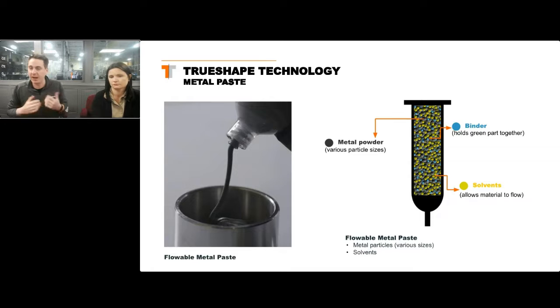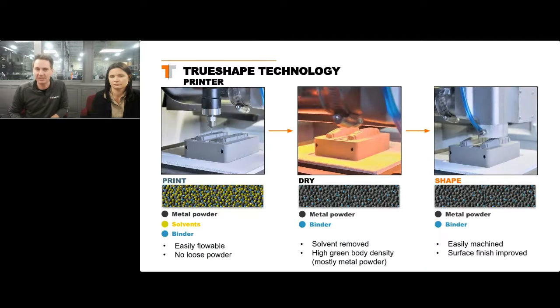And this is really a lot of the secret sauce of what makes Mantle work, inside of this paste. So every single layer inside of our printer, which is built inside of that CNC that I showed you earlier, we are printing this paste. This paste is just being extruded out of a nozzle. It's actually not even heated when you're doing this. It's viscous enough that just with a pump, it can be extruded through this needle to lay down a layer of this material.